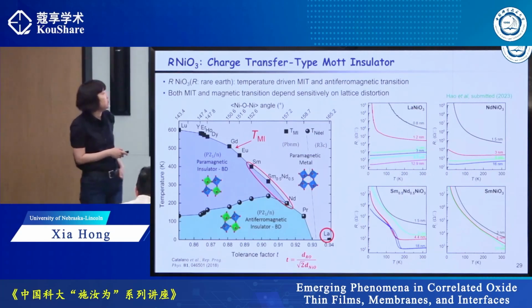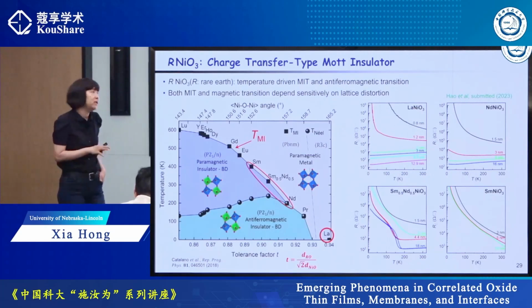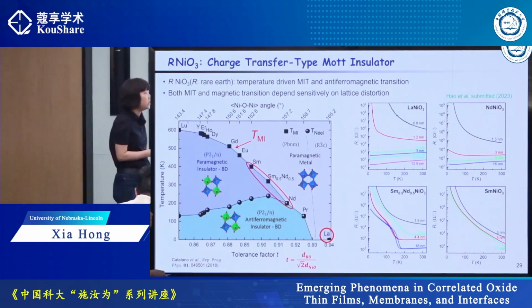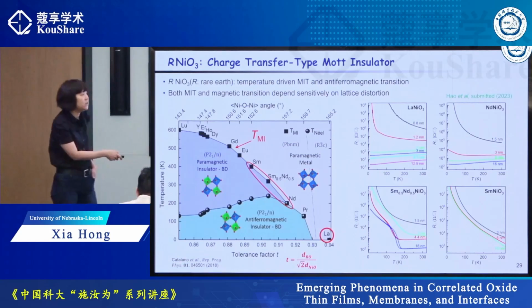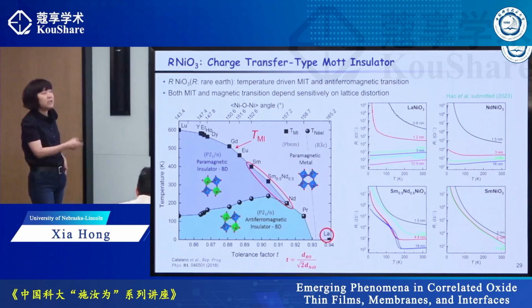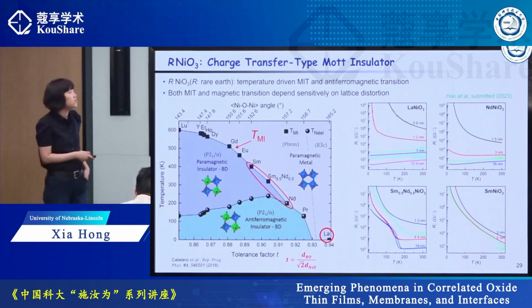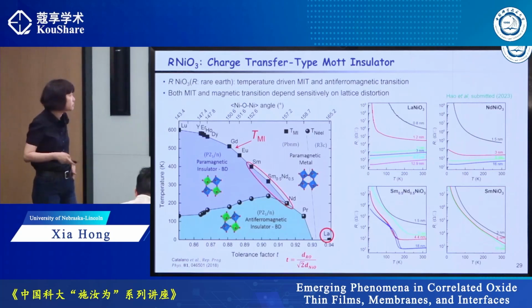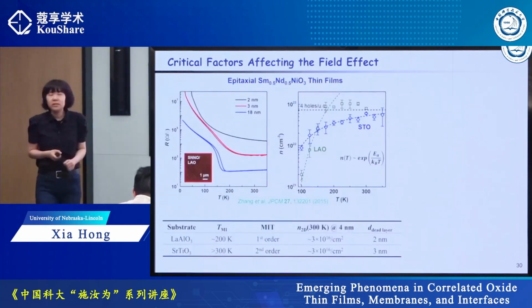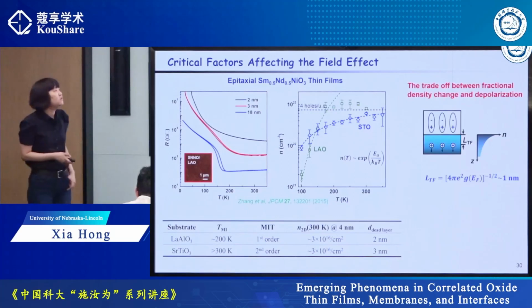If you look here, the first thing is all those samples have a finite size effect, meaning if you reduce the film thickness, there's a metal insulator transition. For samarium nickelate, it is actually insulating for all different thicknesses. But for the other ones, you have a metallic phase at room temperature when the film is thick, and when it's very thin, it becomes totally insulating. So why do we care? Because let's consider what happens for the field effect.